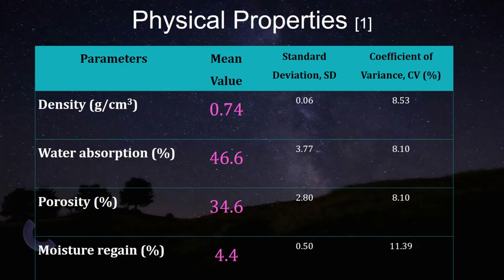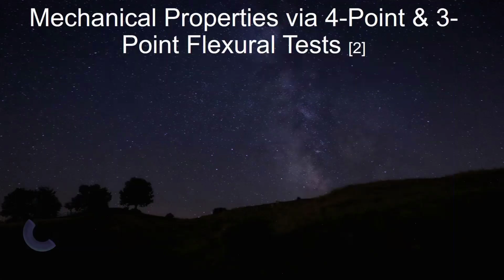By the way, all these tests have been done according to the industry standard and followed by other researchers' methodology. And the water absorption was below 50%, porosity around 35%, and moisture regain around 4.5%. So when we were convinced with that, we went further to the mechanical properties.